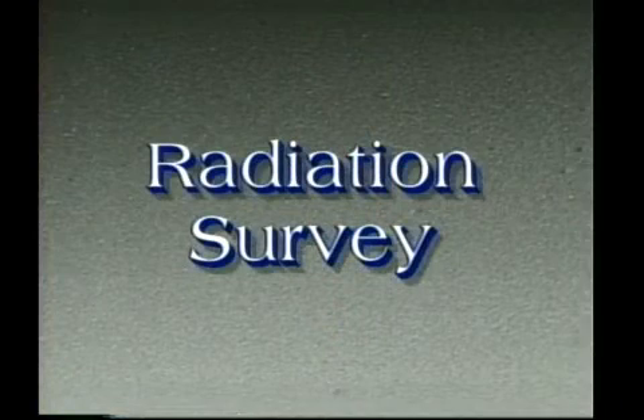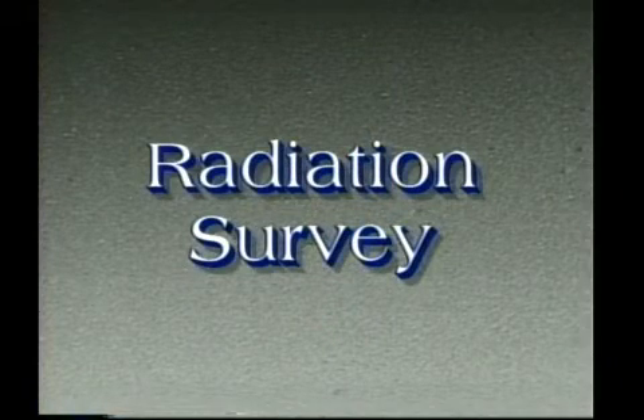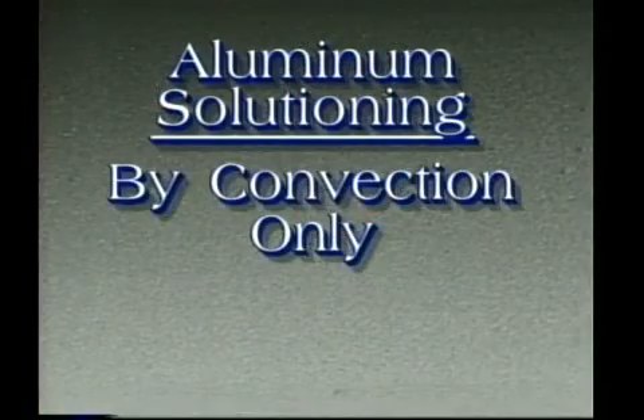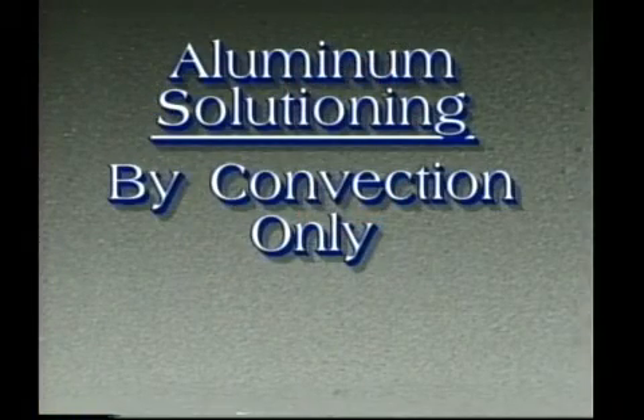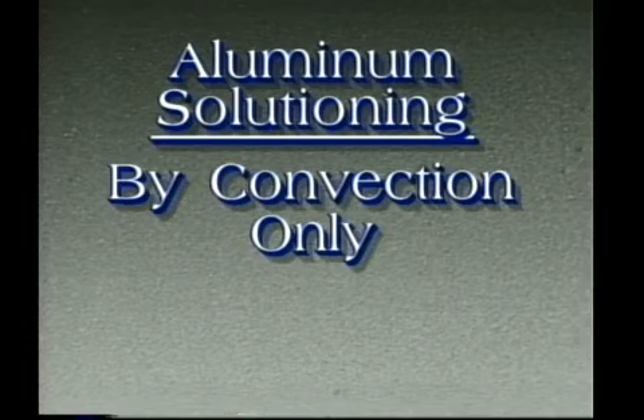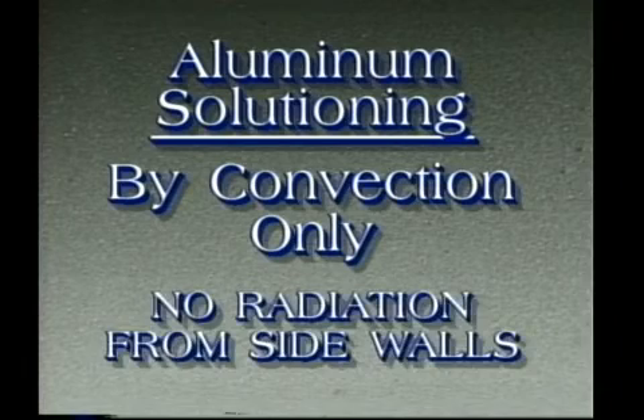One of the most critical operations in the aluminum heat treating plant is that of the radiation survey. As aluminum heat treating furnaces or parts are heated through convection and conduction heating, radiation heat in the aluminum furnace must not be a factor. All aluminum parts in an aluminum solution heat treating furnace should only be heated by convection, by the hot air moving past the part. The part should not be heated by the radiation from the sidewall of the furnace.